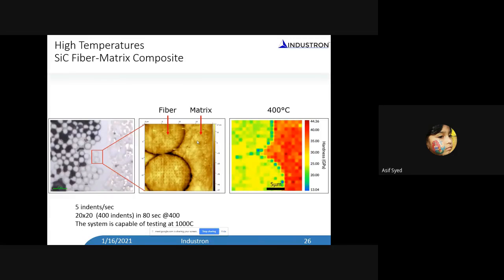For example, you can do 5 indents per second, and within like 20 by 20, 400 indents, you can do it in 80 seconds. And along with this, the heating stage that I've shown before, you can do this at 400 degrees, 800 degrees, even up to 1000 degrees C. So you can do a property map pretty fast using this technique. You can measure the hardness as well as modulus. Both the maps you can do. So not only modulus, we can also do hardness with this technique.